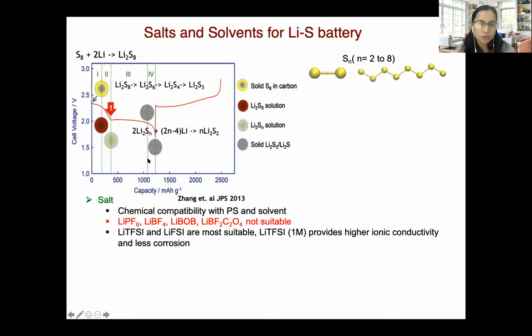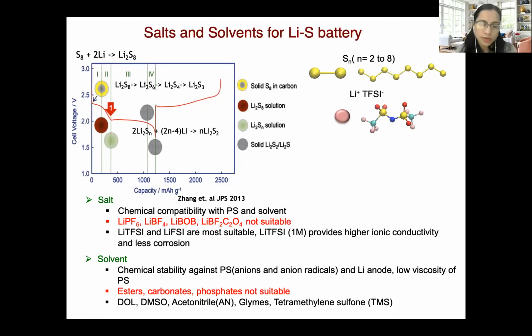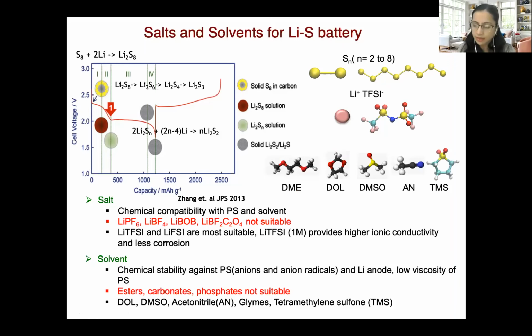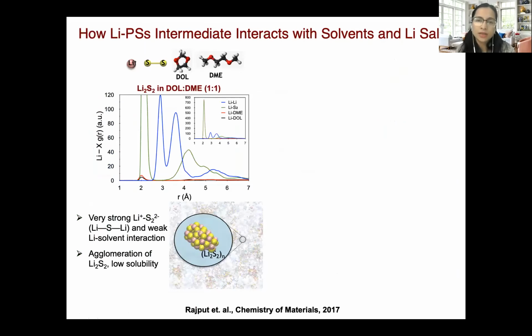The choice of salt is very crucial for lithium sulfur batteries, and most of the traditional salts like LiPF6, LiBF4, LiBOB are known to be not compatible with polysulfide and solvent. And the state-of-the-art salt is 1 molar LiTFSI, which was used in this work. Similar to salt, the choice of solvent is also very important, and several traditional esters, carbonates, phosphates, which are known to work in lithium-ion batteries, don't work in lithium sulfur batteries. There are a handful of solvents which are known to work, and we considered most of them in this work.